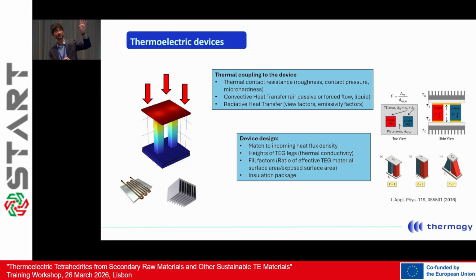And once you have figured out how to fit all of this, you also match that incoming heat flux density into the device itself. So the device, I think most of you know, is all about matching the heat flux densities to the heights of the material as well as the fill factors. And that is how you determine, based on the thermal conductivity of the material, how tall your device is and how much of it you are filling up over here. So the fill factor is the ratio of the effective TEG material surface area to the exposed surface area. And there you can get to very unique TEG unicouples also, and that has been quite reported in literature.